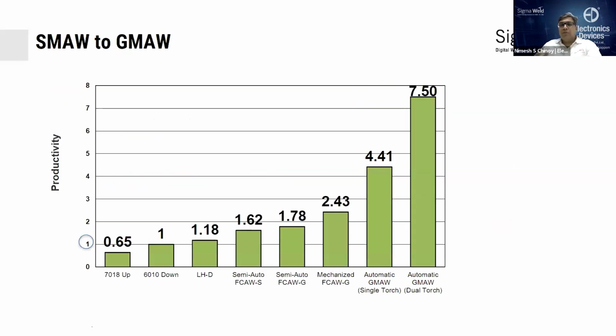When we move from arc welding to MIG or flux core welding, you can see the kind of productivity increase we can get. These are electrode types. So if you look at 7018 welded in uphill position, you will get a deposit of about 0.65, that is 650 grams per hour. If you look at 6010 cellulosic electrode and downhill, 1 kg per hour. Then you look at low hydrogen deposit 1.18. And the minute you start moving into flux core arc welding, you get 1.62. Move into semi-automatic flux core arc welding, that gives you about 1.78.